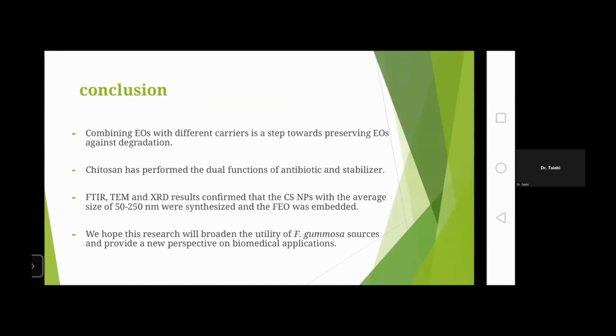In conclusion, combining essential oil with different carriers is a step toward preserving essential oil against degradation. Chitosan has performed the dual function of antibiotic and stabilizer. FTIR, TEM, and XRD results confirm that chitosan nanoparticles with an average size of 50 to 250 nanometers were synthesized and the Ferula essential oil was embedded. We hope this research will broaden the utility of the Ferula gummosa source and provide a new perspective on biomedical application. These findings probably show that Ferula essential oil could be effectively loaded in chitosan to further facilitate its utilization in the food or medical industry.